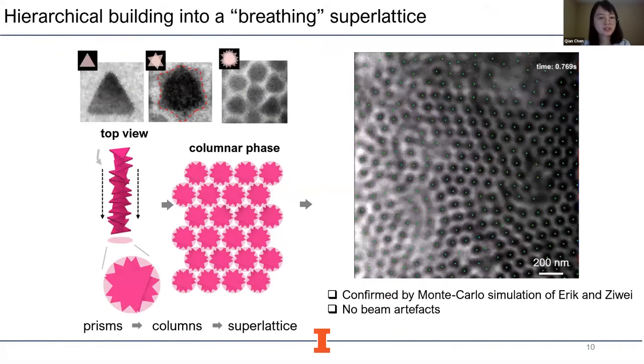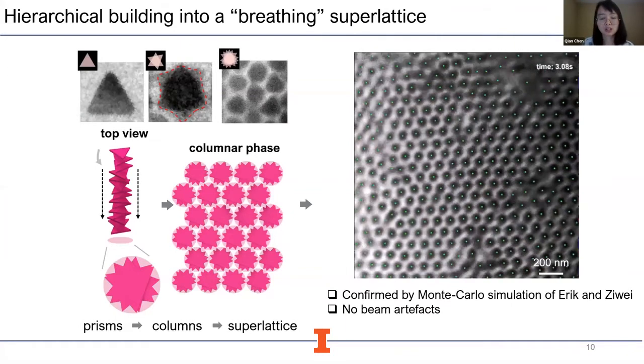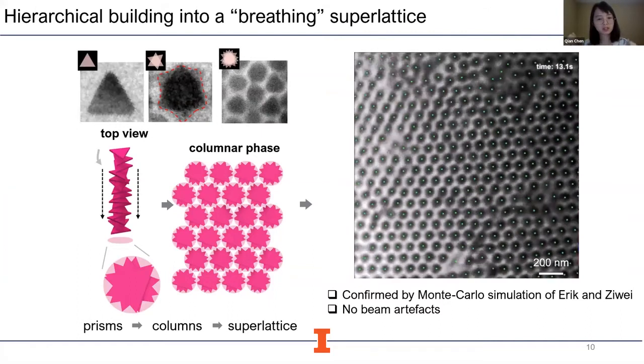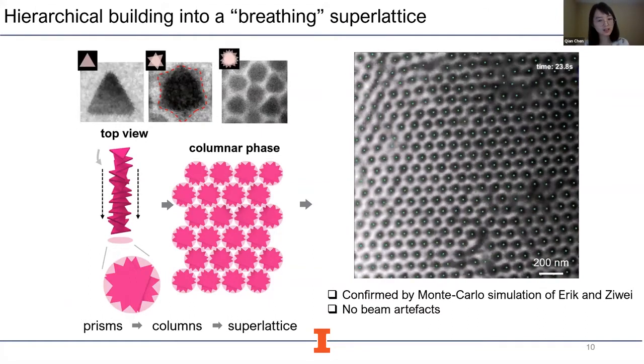Fortunately, liquid phase TEM allows direct imaging, so we are able to capture individual prisms. First they sit flat on the substrate, and then another prism comes flying in and stacks on top of it into a column, but not in perfect registry. This misalignment can build up to make the projection of the column in TEM more and more circular. And interestingly, even after it reaches equilibrium, the columns can still locally vibrate a lattice site as a way to dissipate energy.